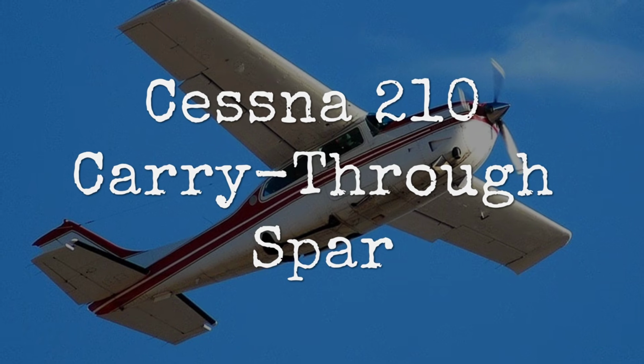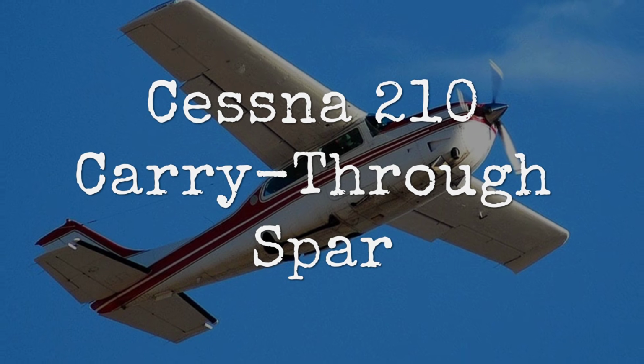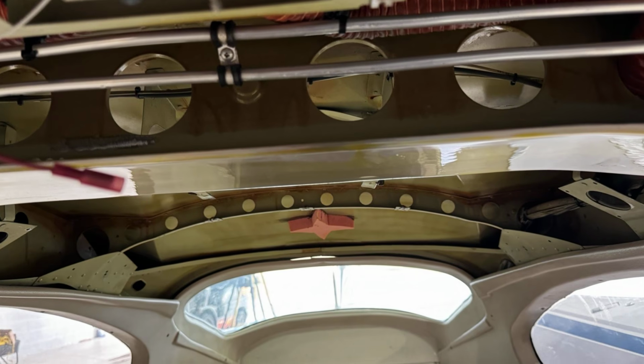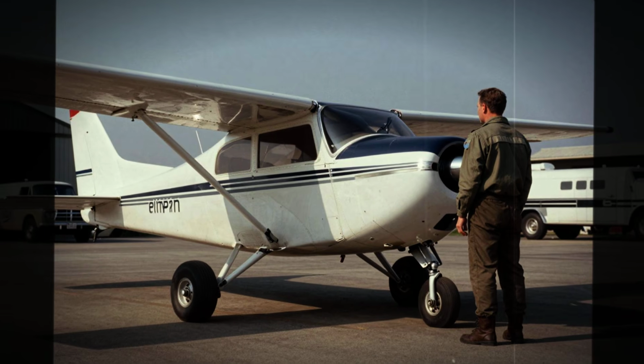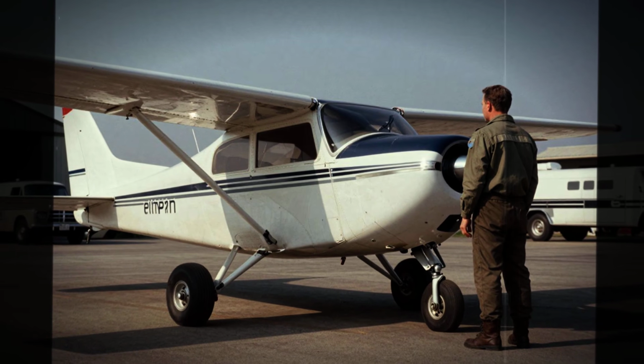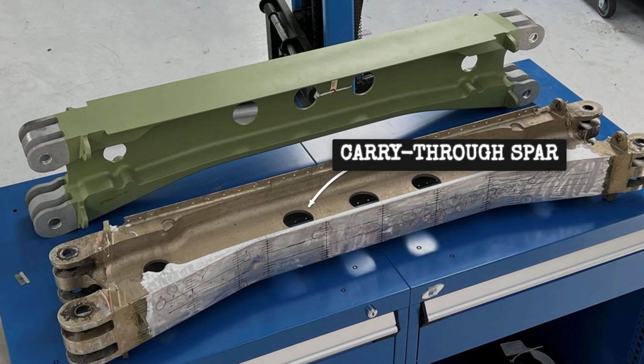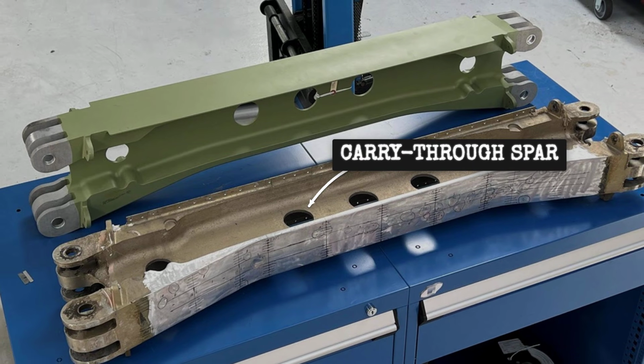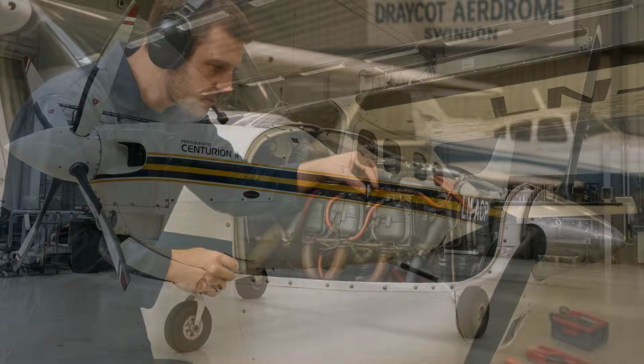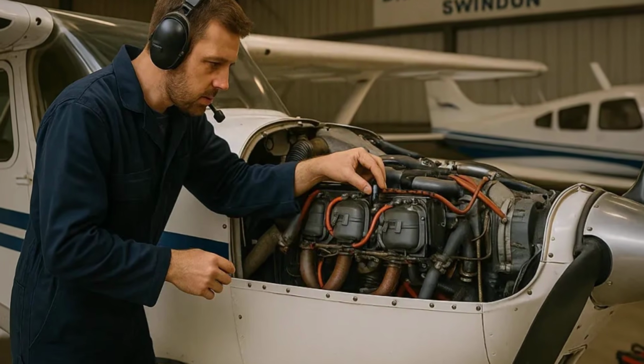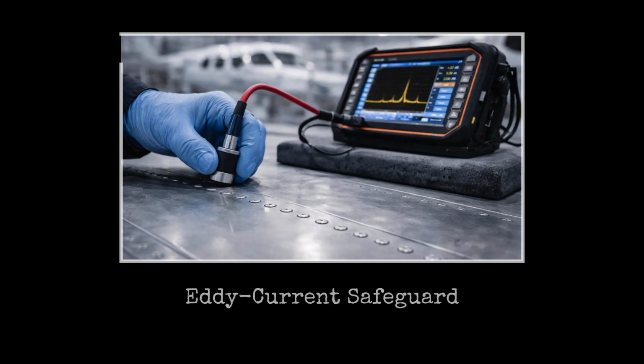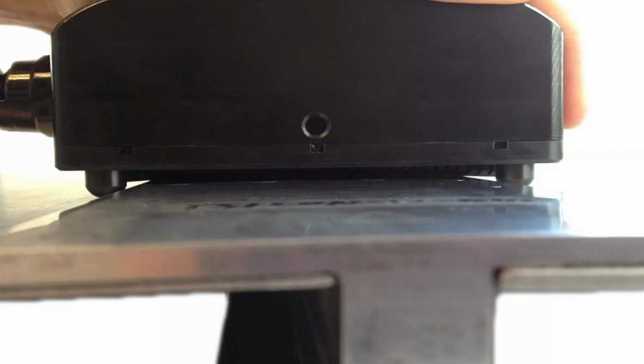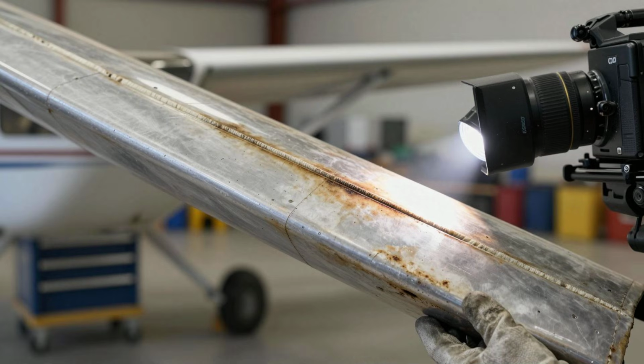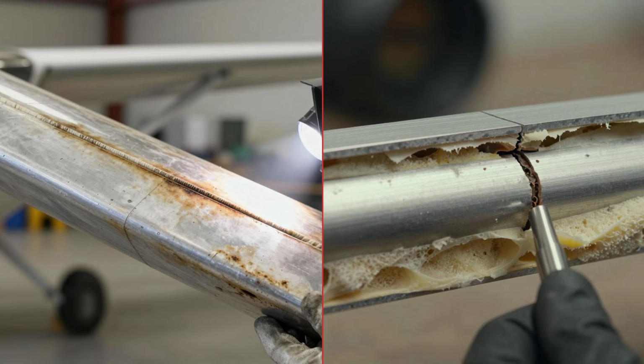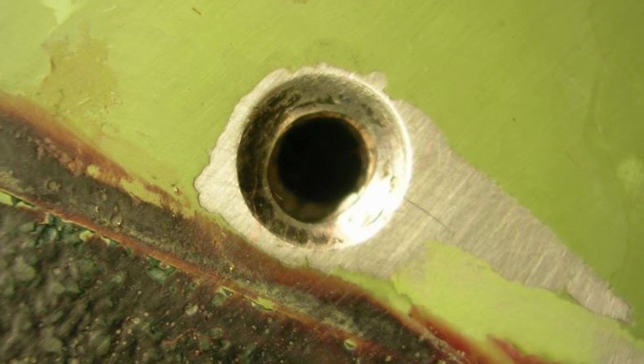The Cessna 210 Centurion's cantilever wing carries every structural load on a single machined aluminum beam running through the cabin. When Cessna eliminated the wing strut in the 1960s, that bracing load moved entirely to this one component, the carry-through spar. There is no backup. Cessna's original maintenance program addressed this with flight hour-based eddy current inspections. Eddy current is the only method capable of detecting internal fatigue cracks before they grow to critical size. A visual inspection of the spar surface finds surface corrosion. It cannot find what is growing inside the metal.